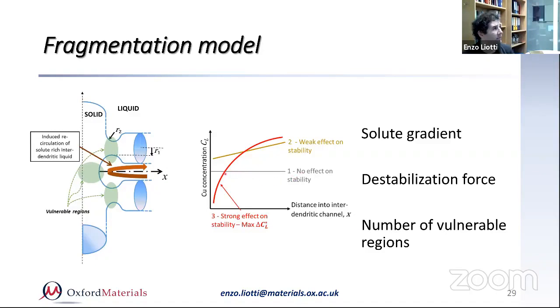If the concentration of the solid would be flat, then even if you destabilize, if you move the liquid, nothing would really happen. If you've got a little bit of concentration gradient, then the effect in destabilizing this vulnerable region will decrease. But if you've got a steep concentration gradient, then the effect of a destabilization force, that could be our electromagnetic steering, is increased, and therefore you've got more chances to break this vulnerable region. So to summarize, what you need to enhance fragmentation is a growth condition that favors the formation of this vulnerable region, that favors the formation of high curvature areas. And also you need a destabilization force, and you need quite a steep solid gradient within the mushy zone.